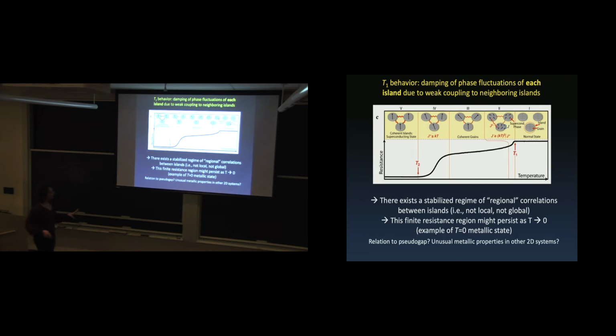So the takeaway here is that, for one, there's different types of correlations that can exist in phase-separated materials. There's strong correlations, or global couplings, which is what you get down here. And then there's something we call regional couplings, which means that the islands are coupled, but not coherently. Okay? They're not coupled enough to have the same phase, but they're coupled enough to influence fluctuations on each other. And so for these sort of regional couplings, you can still influence their behavior. That's one takeaway. The other takeaway is that there's a finite resistance region that can persist as the temperature approaches 0, which may be one example of a 0 temperature metallic state.